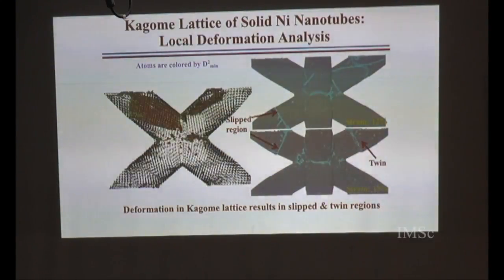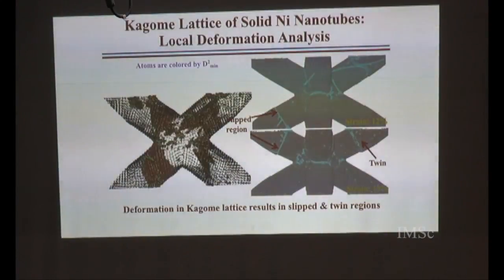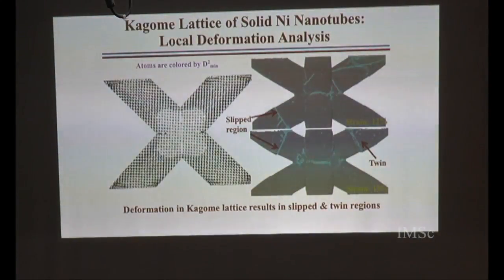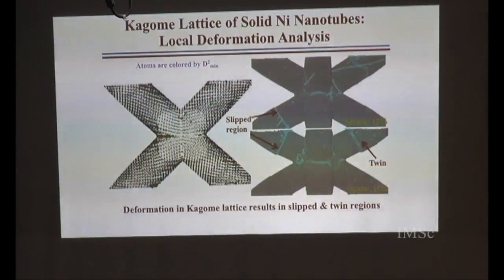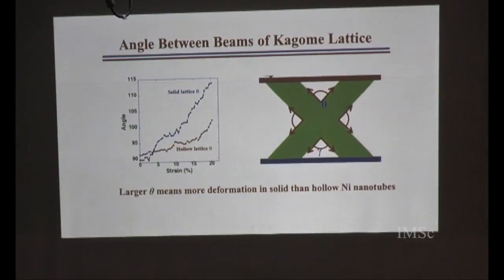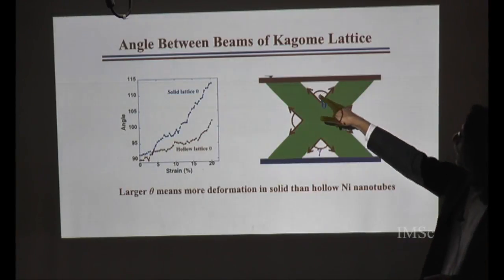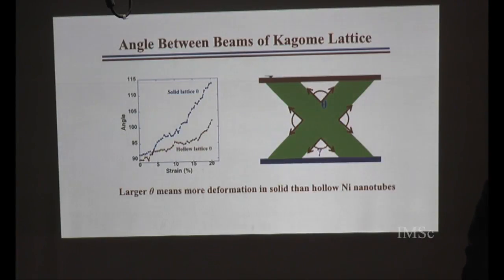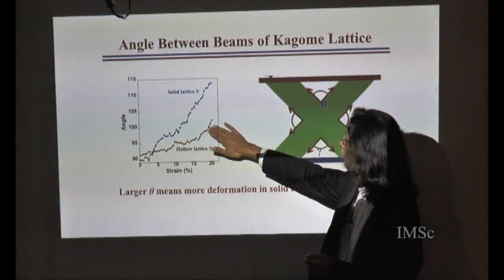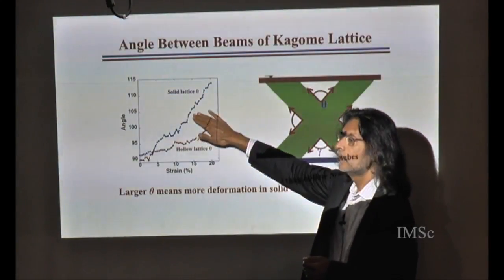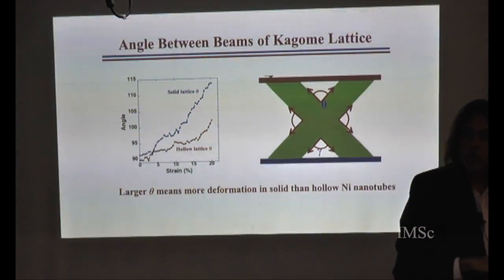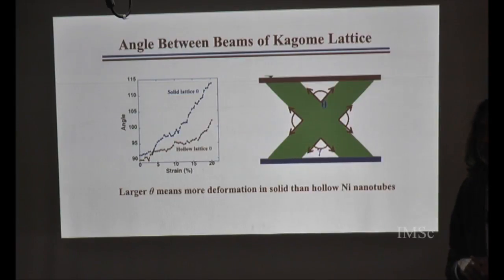We have gone to much higher strain. These systems can be strained to something like 20, 30%, and they respond beautifully. So very robust structures. And we find that one useful variable to describe deformation in this system, a very simple variable, is simply to look at angles between the beams in the two cases. So in the case of hollow lattice, you can see these angles are much smaller. In the case of solid lattice, the deformation is much more and the angles are much larger.